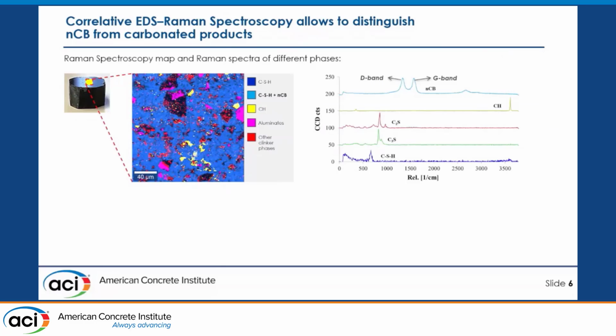Before I move forward to the scalability of this material, we explored at first how nanocarbon particles form that conductive network in our material. So we used the correlative EDS and Raman spectroscopy techniques, and then EDS gave us easy access to differentiate nanocarbon particles characterized by specific Raman spectra with D and G bands, and then differentiate them from other clinker phases or hydration products.